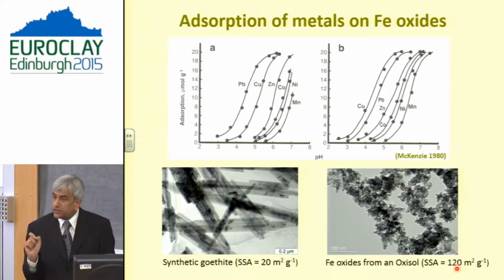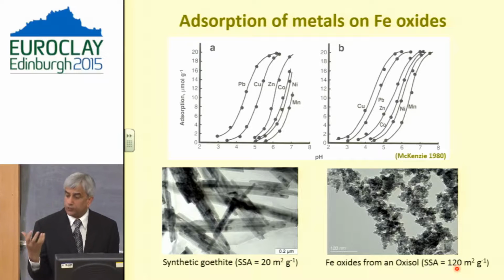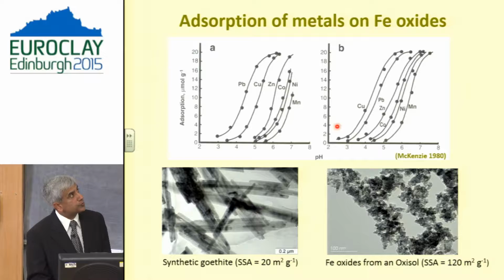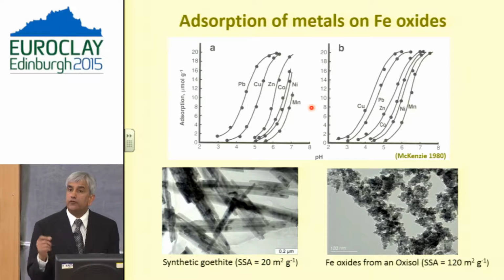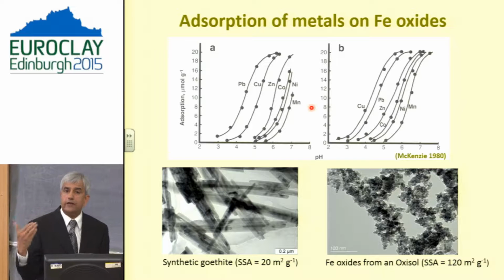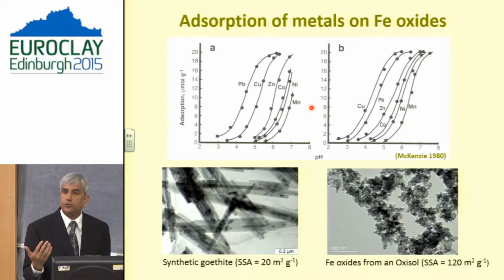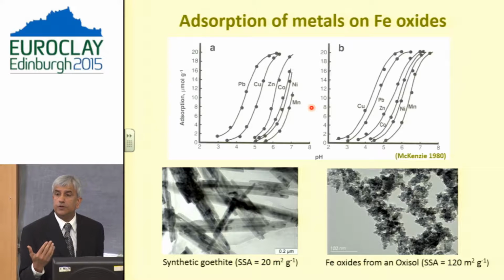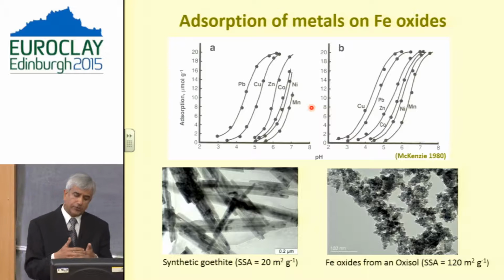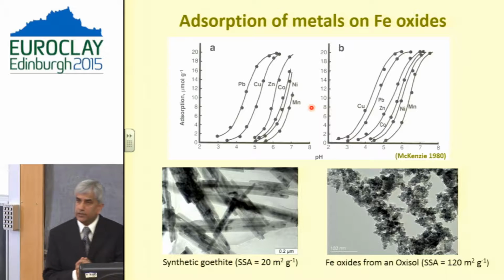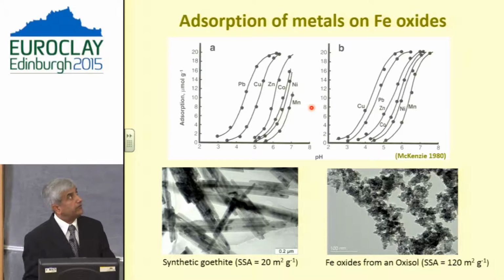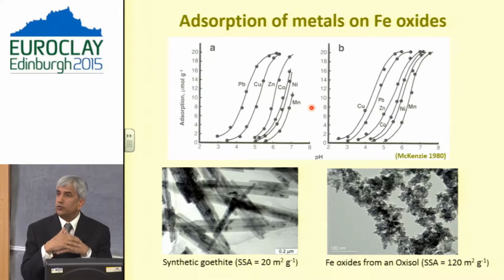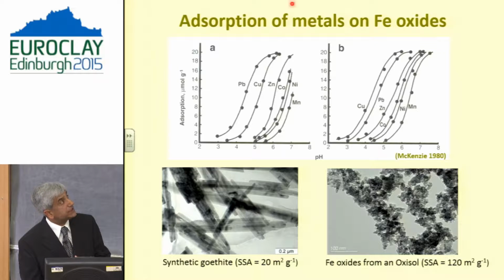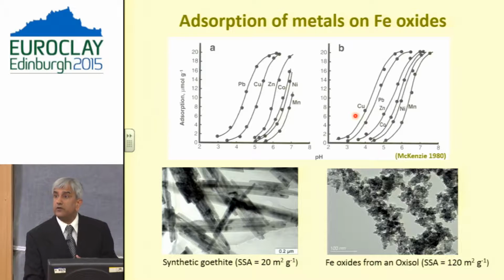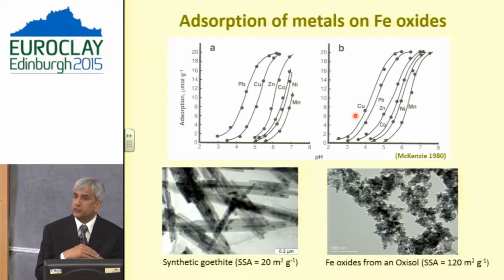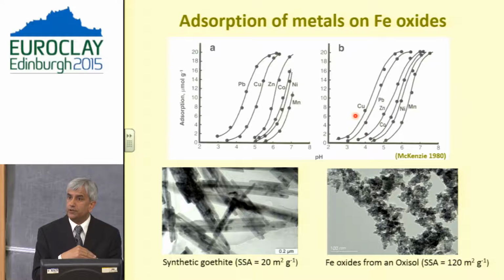And what it does is, when that sort of material is present in the soil system, the adsorption of a lot of these trace elements is going to be much higher than what you would expect from the pure species. So not only do you have the incorporation of lots of metals in the structure of iron oxides, you will have adsorption or association of a lot of these trace elements with iron oxides as a result of their adsorption on the surfaces of these minerals.